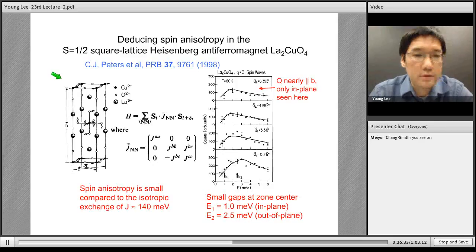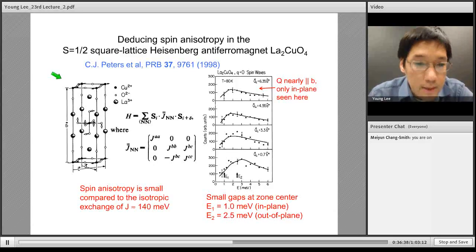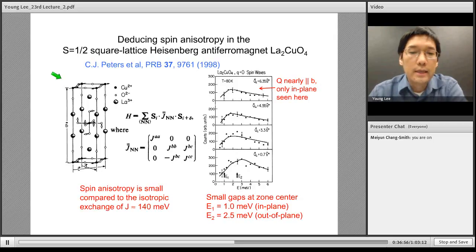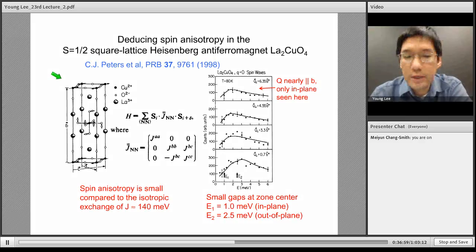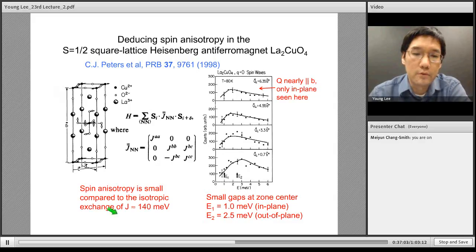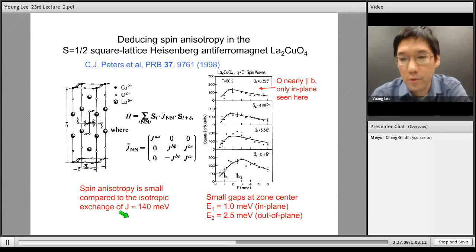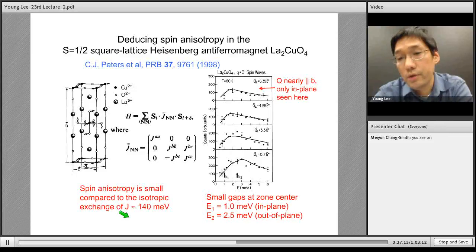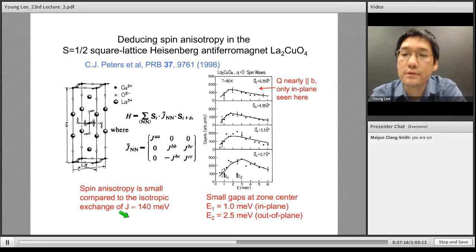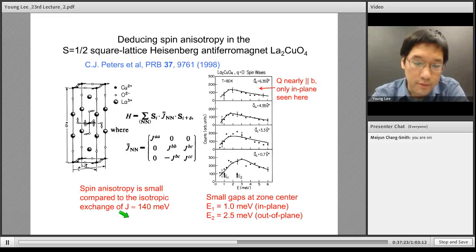Here's the crystal structure for such a system. The coppers are shown with these spins on the small black atoms. They're on a body centered tetragonal structure, but it's really a square lattice of these copper ions. To first approximation, this is a very good Heisenberg system. So J is almost isotropic, and this isotropic J is very large, about 140 millielectronvolts. But if you look at low energies at the spin waves, you also see gaps. That means there are some anisotropy terms, and these could affect the low energy physics.